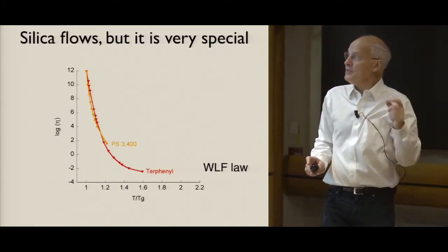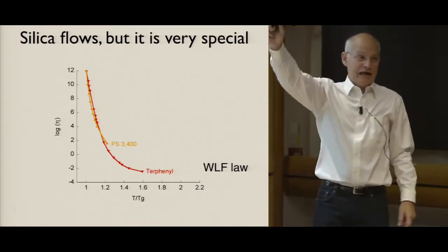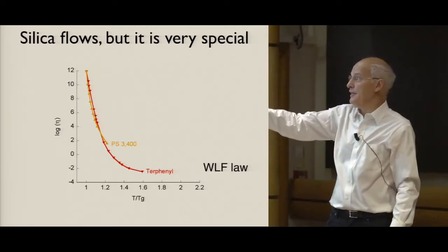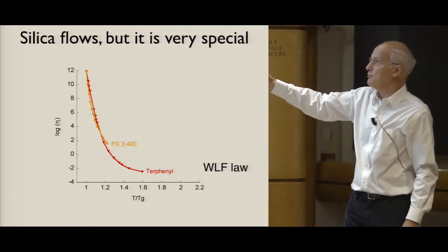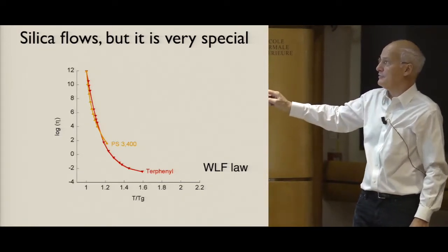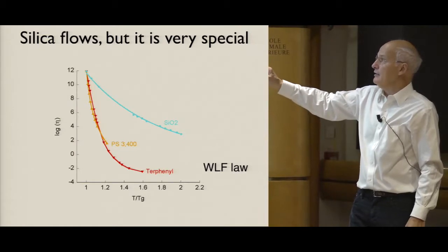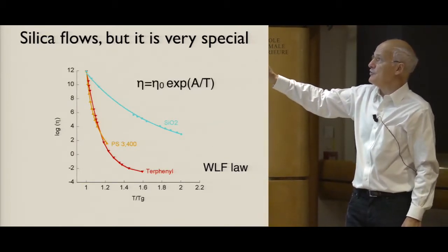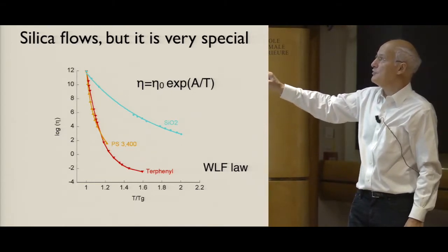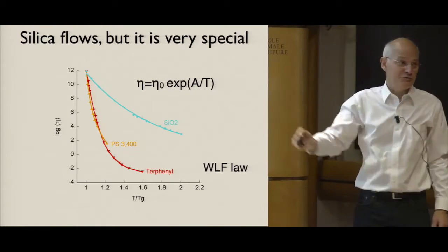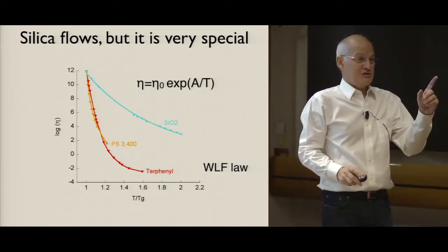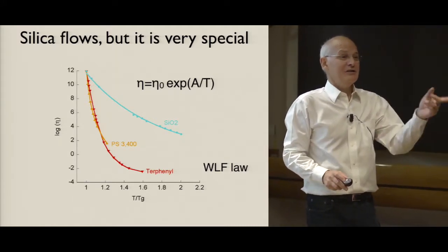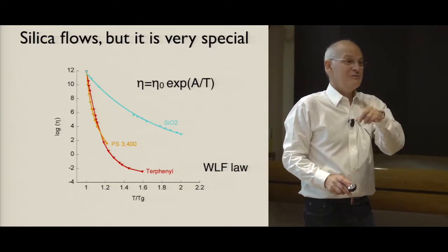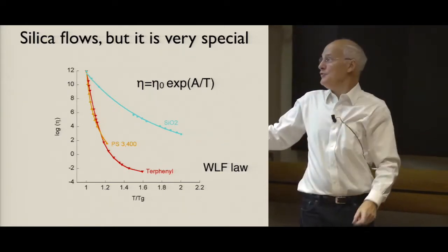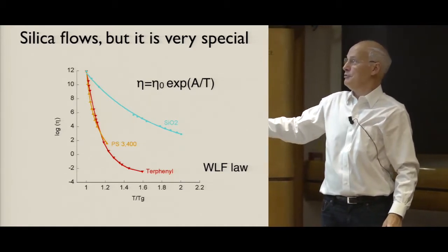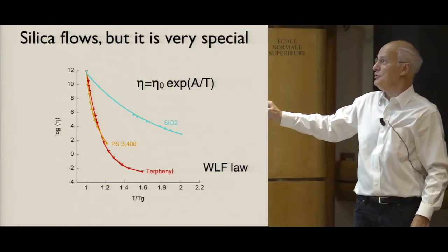However, silica does not behave the same way. So the glass does not behave like all these organic glasses. All organic glasses, if you renormalize the glass transition temperature, will behave the same because they obey this non-Arrhenius law. Whereas silica changes viscosity near the glass transition very, very smoothly, the transition is not abrupt, and it obeys a simple Arrhenius law. And so for the physicist, the fact that something obeys an Arrhenius law, that it's a thermoactivated process, seems not very interesting. And so most physicists were interested in the other transition.